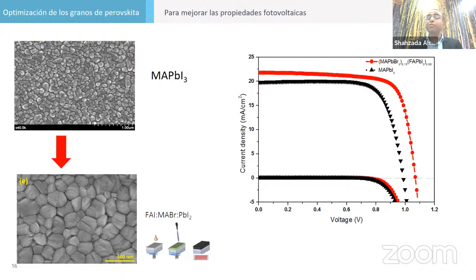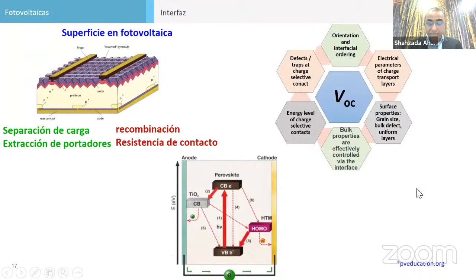And with the mixed perovskite, people were very happy that we had a higher performance. But now the community, after working on it, realized that this is very good, but it's also a double-edged sword because after some time there is a phase separation, because we are mixing two halides. The halide gets shifted, gets separated, and the device performance is lower. It's just symbolic here of how the performance increases from methylammonium to mixed perovskite.